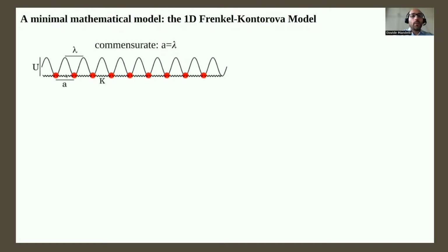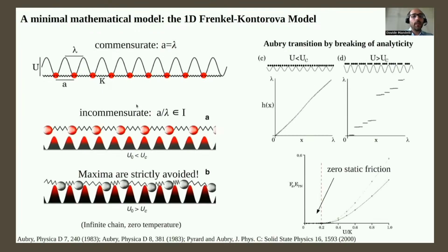The static properties, or the ground state configuration at rest of such a chain, is trivial for the commensurate case. It is shown here, but the problem of finding the ground state becomes quite complicated for incommensurate interfaces, so an irrational value of the ratio between a and lambda. In particular, the ground state becomes very sensitive on the choice of the amplitude of the substrate potential. And Aubry, back in 1983, actually demonstrated that upon increasing the substrate potential, the ground state undergoes a